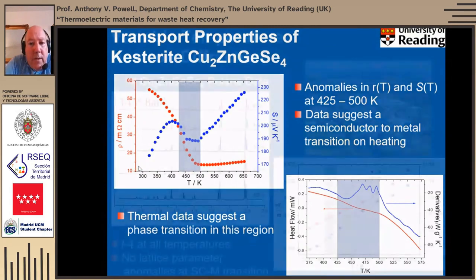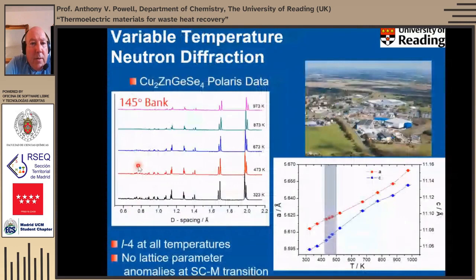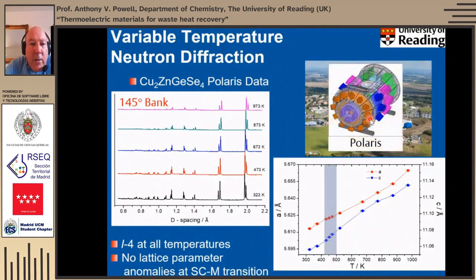But to study this, we took this, Jesus mentioned the ISIS neutron facility. We took this to the Polaris, which is an instrument within this aircraft hangar type facility here, which is one of the Target Station 1 instruments. Polaris is a multi-bank instrument. So this is just one bank from Polaris as a function of temperature. And as you can see, surprisingly, there's very little variation in the neutron diffraction patterns as we heat this up. And if we actually do the Rietveld refinement, we find that when we get through this region, this gray stripe showing the region where those electronic anomalies are, we see no lattice parameter anomaly either.